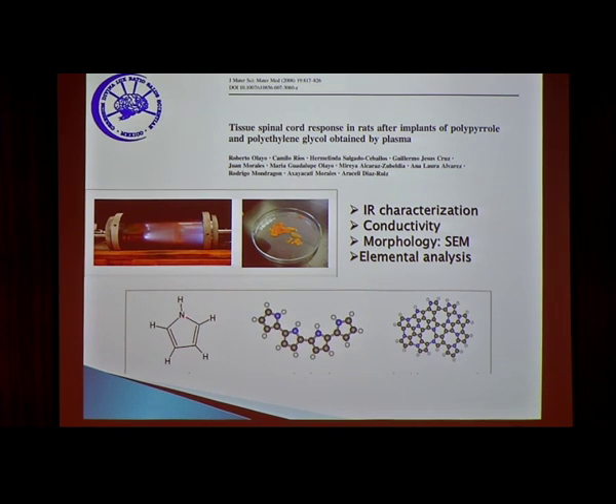So here is the material, and this is the pyrrole molecule, and then when it is subject to the polymerization process, it forms these kinds of structures, or even this other kind of structure, a more cross-linked polymer. And of course, it was characterized by chemical composition, for example, the nitrogen and carbon bonds and the carbon-carbon bonds were characterized by infrared spectroscopy. We also used electron microscopy to see how they look at the nanoscale.